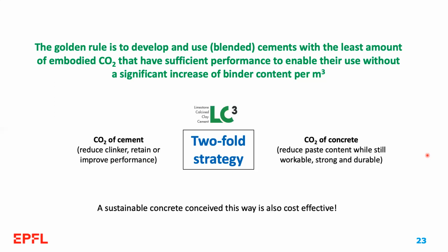And this is where the LC3 technology becomes a breakthrough because it's, to my knowledge, one of the few solutions, if not the only one, that enable a substantial clinker reduction while retaining the same mechanical performance as PC. And this is very important because it's able to link very efficiently the two components of the twofold strategy. Also, a sustainable concrete conceived in this way is most of the time cost effective because we are reducing in these two elements of the twofold strategy the amount of cement, which is the most expensive component of concrete.